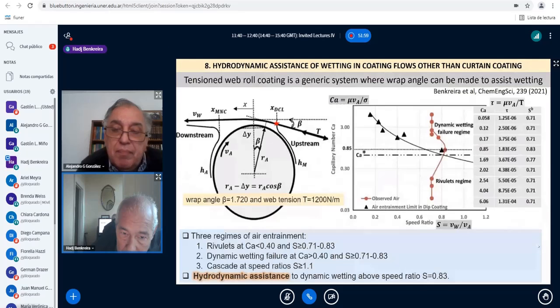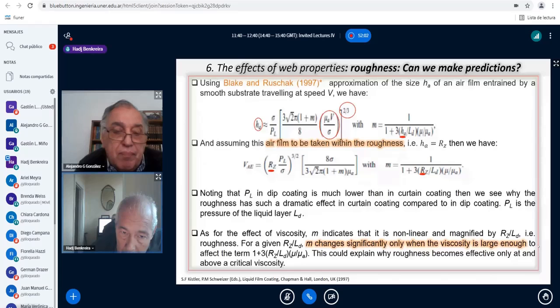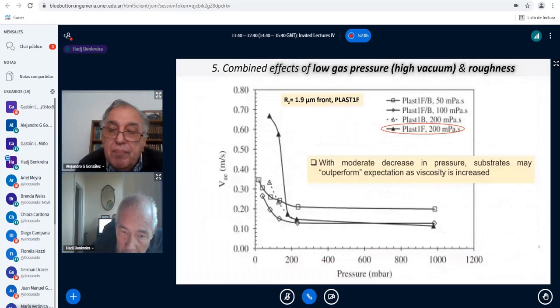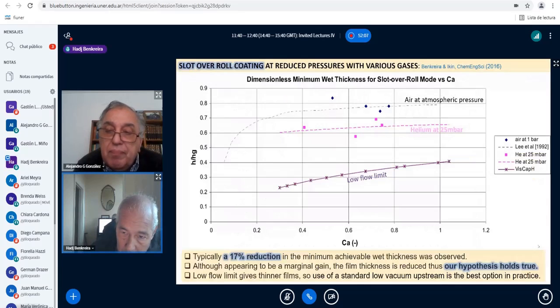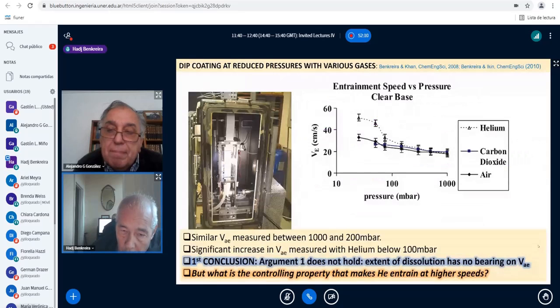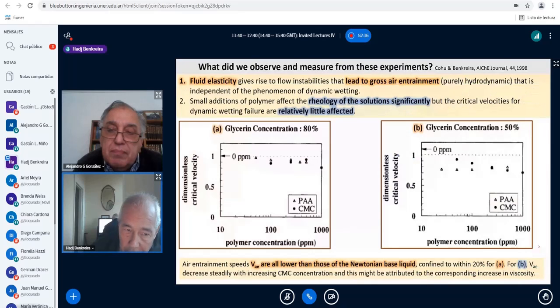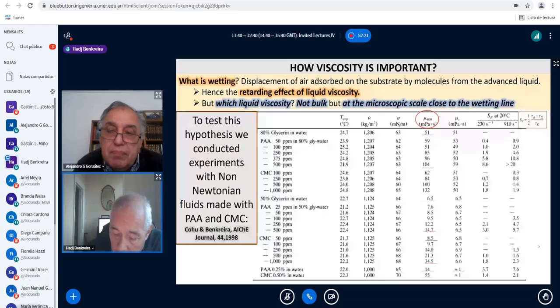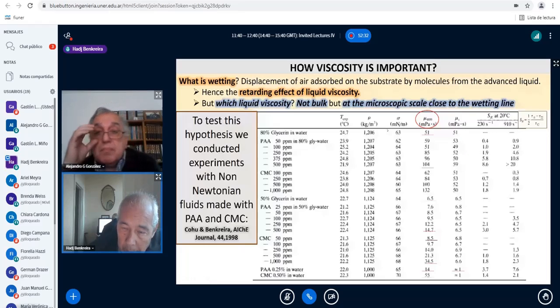by using these CMCs and PAA, the molecular size is very large, and so therefore it would not be effective near the interface. And this is why I refer to the solvent viscosity. So if you have a solution of a liquid with a polymer of high molecular weight, you should be able to find exactly the same behavior as we describe in here.